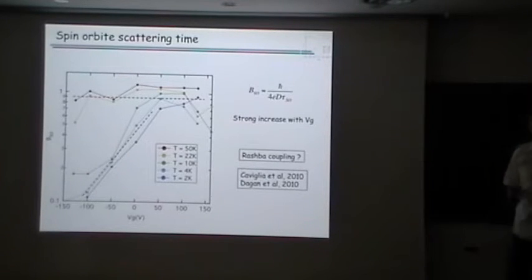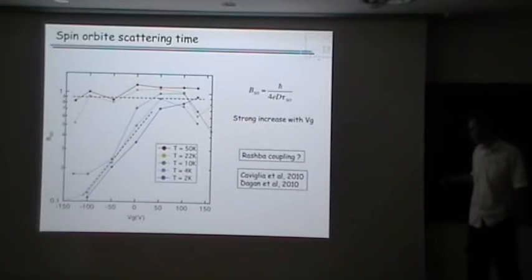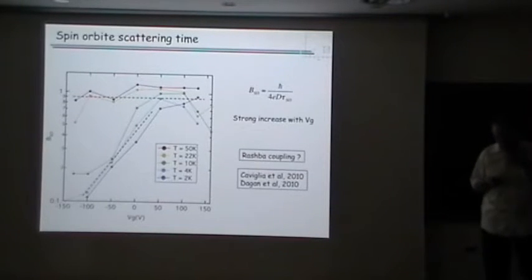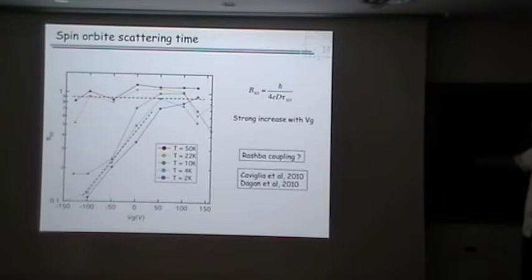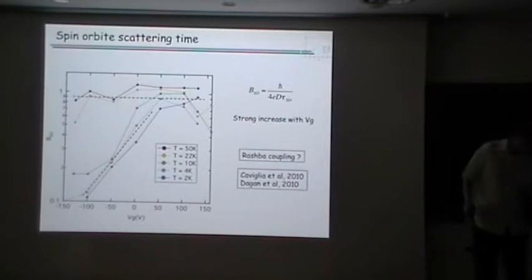Now, what about the spin orbit? So at high temperature, the spin orbit is completely flat, and you don't expect weak localization corrections, so forget it. But at low temperature, what you see is that tau spin orbit goes up and then flattens or maybe goes down. Again, the gate voltage dependence is rather important. And in these two papers, people have claimed that, in fact, you have two regimes. One where you have the regular spin orbit scattering for localization, that is just the potential scattering from the impurities. And in the other regime here, we have a Rashba type of spin orbit scattering.